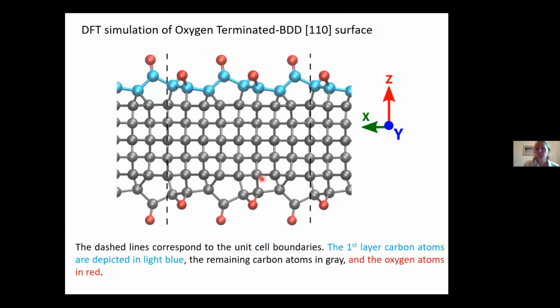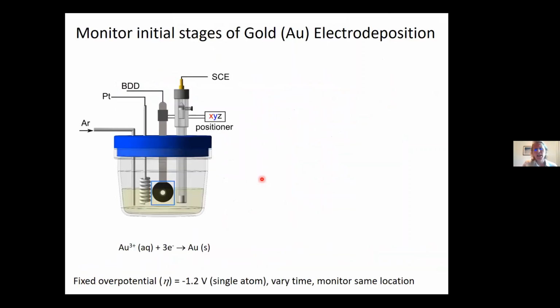So we work with our theory colleagues at Warwick in chemistry, and we're looking to now simulate the structure of the BDD, because at the surface it's going to be terminated. Everything we do is on oxygen terminated diamond. It's a very stable form of termination. We don't use hydrogen termination for these studies. And to start off with, what we decided to do is look at initial stages of gold electrodeposition.